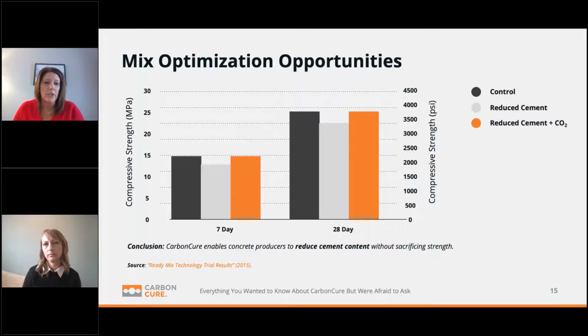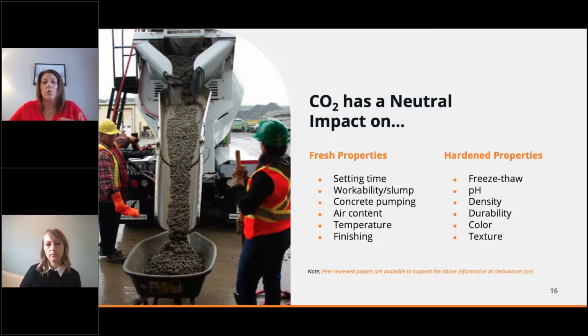The bar next to it shows that same mix with 5% cement removed. And as you can imagine, you take out cement, you're going to see a bit of a drop in strength. But then that orange bar is that same mix with the reduced cement plus the CO2. And what we're able to do is get that mix performing as it was before we took out any cement just by adding CO2.